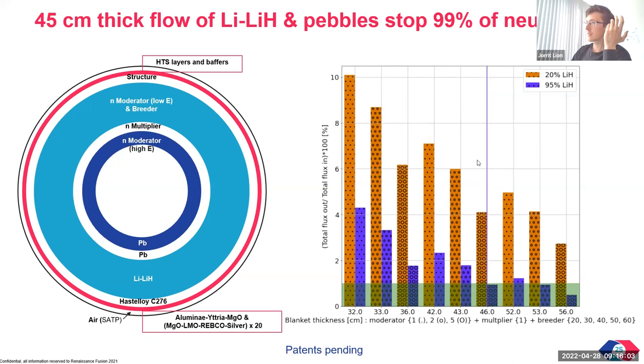The trick here is that the much larger thickness, 1.5 meters, is for pure lithium, I believe. The trick here is to use lithium hydride. So how do you most effectively stop a neutron? Well, you first need to get it from high energy to lower energy, but then for the low energy interactions, the interaction cross-section is highest if the two particles have equivalent mass. Now, what has equivalent mass to a neutron? A hydrogen atom. So having lithium hydride in your bulk material, the hydride is really good at stopping the neutrons, at least from medium energy down to the energy where they're absorbed by the lithium and breed tritium.